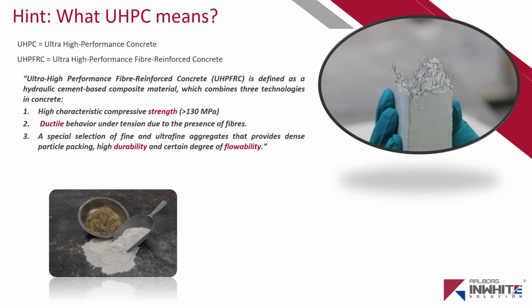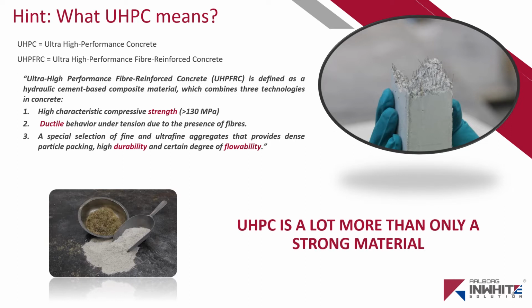The first one, high characteristic compressive strength, which is more than 130 megapascal; ductile behavior under tension due to the presence of fibers; and a special selection of fine and ultra-fine aggregates that provides dense particle packing, high durability, and a certain degree of flowability. The most important message about UHPC is that it's a lot more than only a strong material. It is a material with properties between steel and concrete and with an outstanding durability.